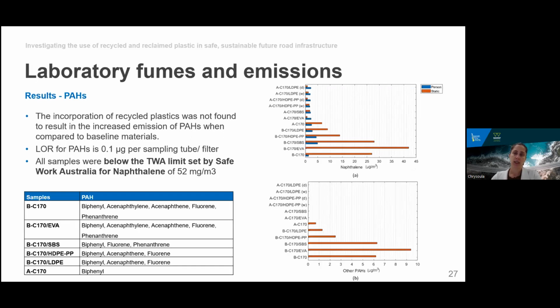In the case of PAHs, the incorporation of recycled plastics was not found to result in the emission of naphthalene or other PAHs at concentrations greater than those emitted by the commonly used materials. Naphthalene is the only PAH for which Safe Work Australia has set an upper exposure limit. The naphthalene emission of EVA modified binder, which was the one found to emit the greatest amount according to the static sampler, was found to be 0.08% of the set limit by Safe Work Australia.